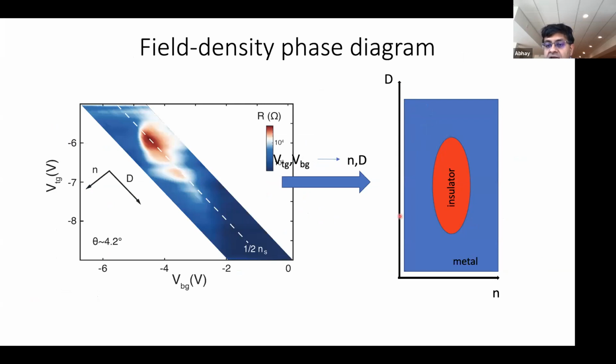As a function of electric field and density, we found that there is an insulating phase which exists over a range of electric fields and disappears for very small or very large electric field. So there's a metal to insulator transition. And so if I look in this as a function of electric field and density, there's a region of insulating behavior which is around 1/2 filling as a function of doping and within some bounds for the electric field.